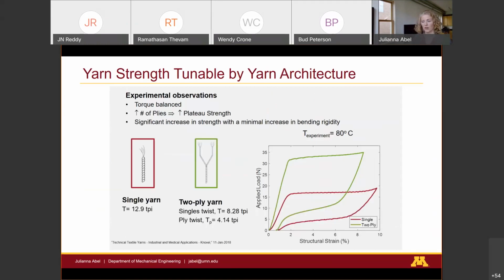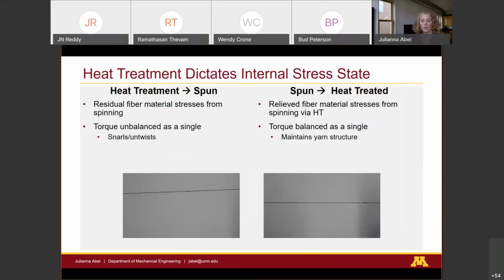Additionally, we can tune the architecture to go from a single ply to 2-ply, and that's going to scale our forces and slightly reduce our structural strain. And we can decide when we heat treat these. If we heat treat the yarn and then spin it, we remove all those residual stresses initially, but then we introduce them in the spinning process, and we have a very active yarn that wants to furl.